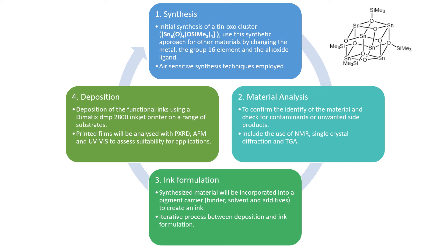The next stage involves material analysis to confirm the identity and properties of the material. This will involve using NMR, single crystal diffraction, and thermogravimetric analysis. The synthesized material will then be incorporated into inks as a pigment before being deposited using an Dimatix dmp 2800 inkjet printer on a number of different substrates. The resulting thin films will be analyzed by powder X-ray diffraction, UV-Vis, and AFM.